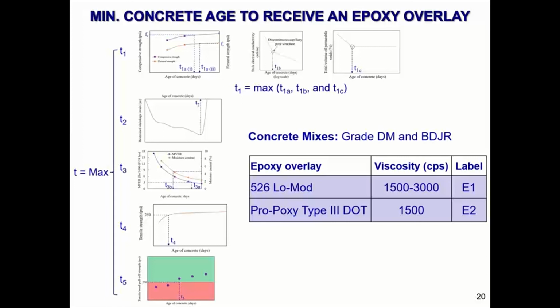They looked at time to cracking, which is T2. They looked at time to reach an industry standard for moisture vapor emission rate, which is T3. They looked at T4, which was the time for the concrete to reach 250 psi tensile strength, which is required to pass the overlay pull-off strength test. And they lastly looked at T5, which is the time to reach 250 psi bond strength between the epoxy overlay and the concrete.